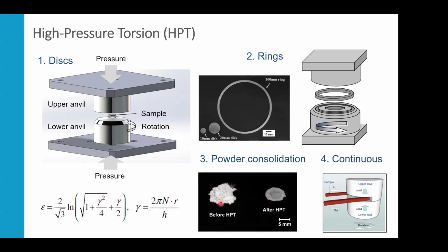For example, here we are looking at titanium oxide powders, and even hard ceramic materials like titanium oxide can be sintered to very high relative density, very close to 100%, and with very good control of impurities, because the limitation is only the oxide. For example, if these were metal particles, then only the surface oxide in each particle will be introduced. But since we don't increase the temperature, we don't induce oxidation from the atmosphere. We don't need to control the atmosphere. And because the sample is constrained, in general, most of the air will be driven out by itself by the pressure. So it's a very nice way to synthesize, especially in the academic field, specialty alloys or ceramics or oxides or some other interesting materials that have also been studied in recent years, like photocatalysts or high entropy alloys.